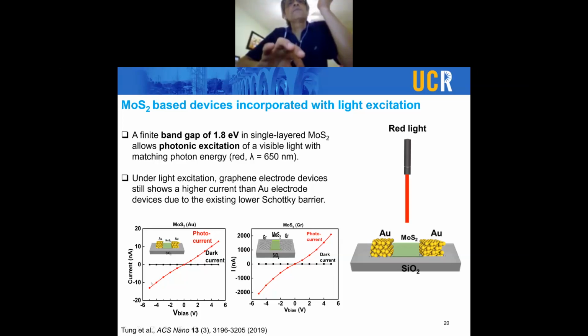And once again, you can see the benefit of light over dark, both in the case of just the gold electrodes with MoS2 as the semiconductor channel, or the graphene electrodes with the MoS2 as the semiconducting channel. This is the dark current, that's the photocurrent. And once again, comparing the photocurrent versus dark current, you can still see a very high current output, which is telling you that the conductivity of MoS2 is improved by using this platform.